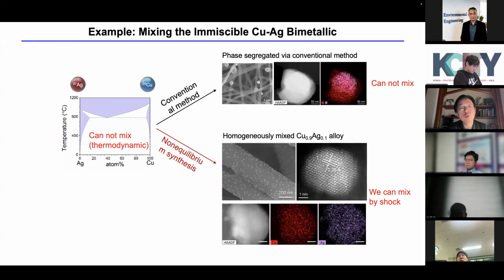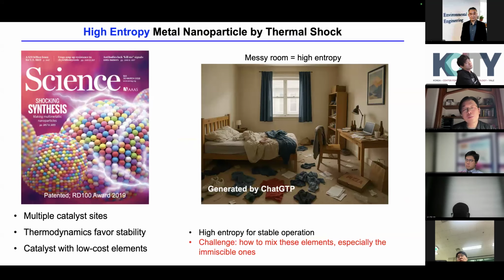For example, silver and copper here, if you look at the phase diagram in the bottom, it's white, which means they don't mix, they don't like each other. And actually, when you make this catalyst using the traditional method, they don't like each other. But if you use the shock method, you can see they're homogeneously mixed. They're basically trapped in these nanoparticle structures. Now, with that, you can even further design a catalyst, something called a high-entropy catalyst.